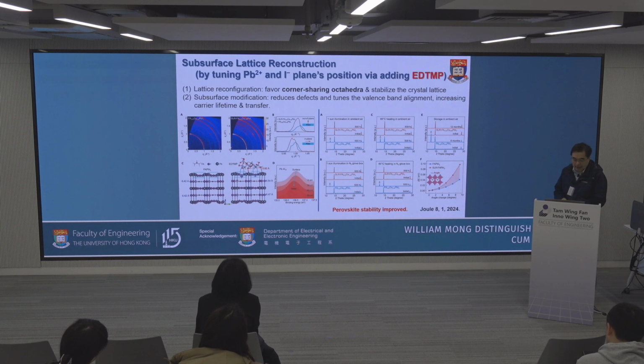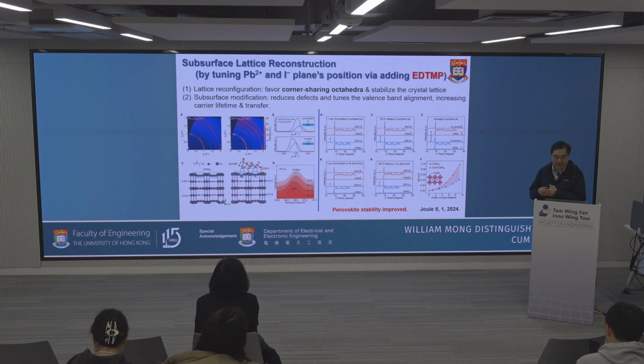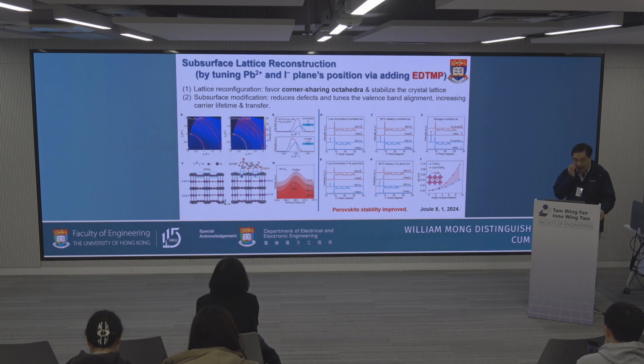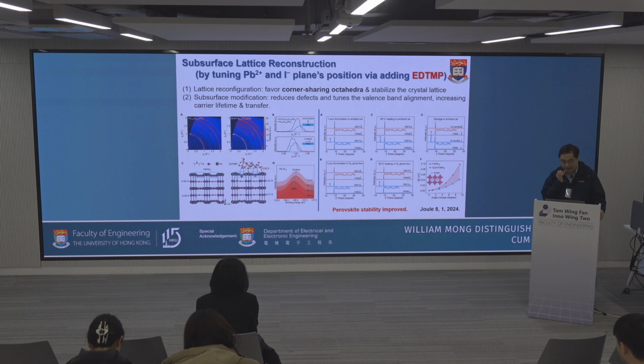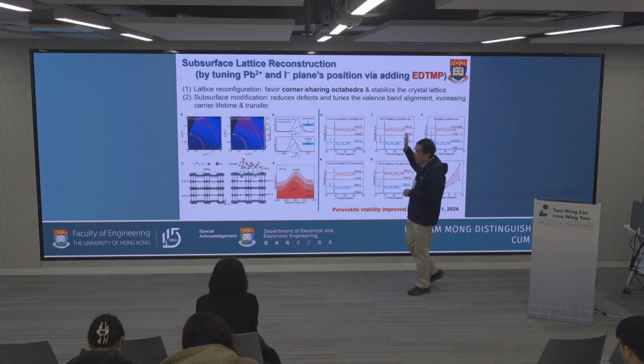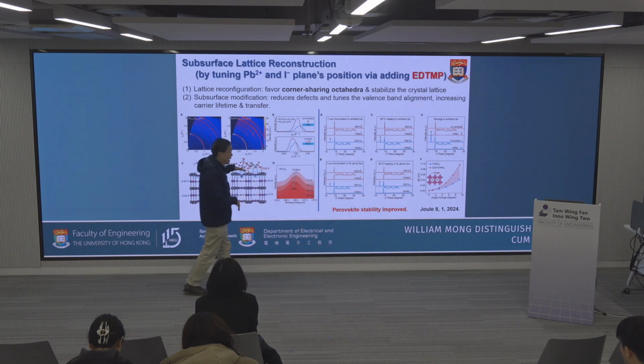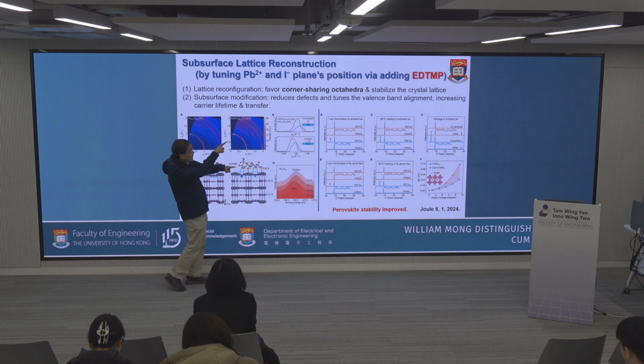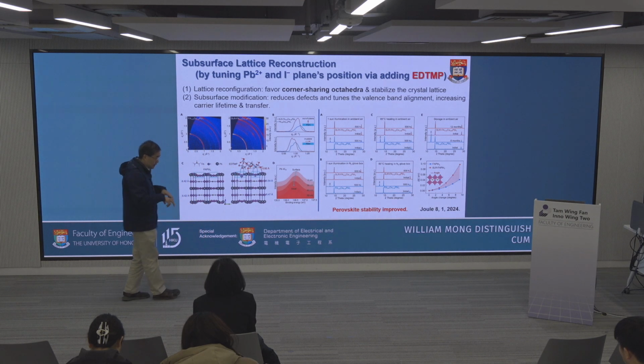Next, with this substrate, with the stress addressed, we still want to address a further issue that we have at the surface, at the boundary of the perovskite. Even when we have a good bulk perovskite, we still have the surface and boundary. They are the source of the defects, degrading the device performance as well as stability. So what we do is introduce the small molecule EDTMP. We are not just coating the small molecule on top to suppress the defects. We actually would like those small molecules mounting on the perovskite surface, making them become the corner share structure.